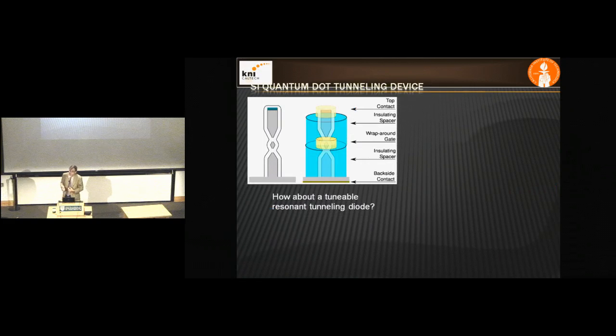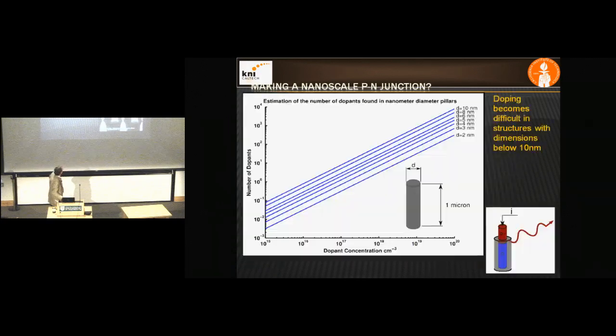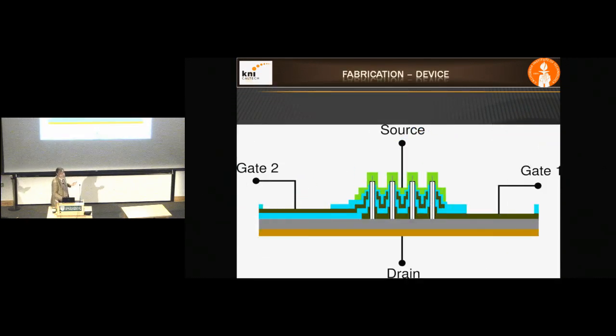One of the problems of this is if you make these structures so small, you can't dope them anymore. Because if you look at it statistically, if you dope with 10 to the 19 dopants per cubic centimeter, and you calculate how many you should have in a 2 nanometer structure, you'll end up with a couple. Okay? It doesn't give you enough statistics to have a Fermi level and do the p-n junction thing that we're so used to. Okay? So we need to introduce carriers by gates. We have to build structures like this that have 2 or 3 gates on them.